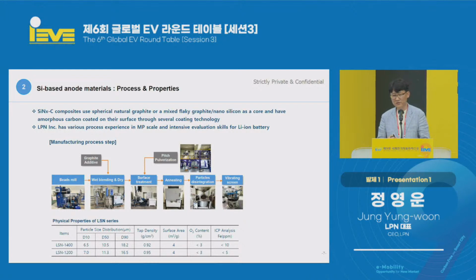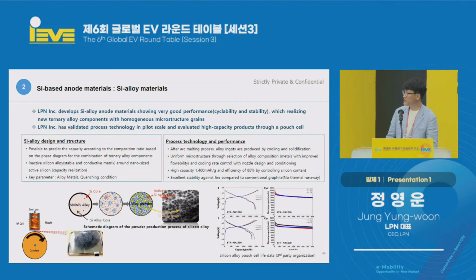So the second thing we developed was doing it without pulverizing. We have to create nanoparticles of silicon without pulverizing. And then we have developed this technology. When we are cooling this, extremely saturated particles will come up again, and that should be prevented from getting bigger than nano size. And if we can quench at the moment, we can have the nano size without pulverizing.